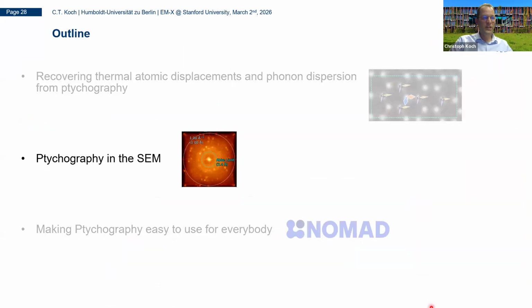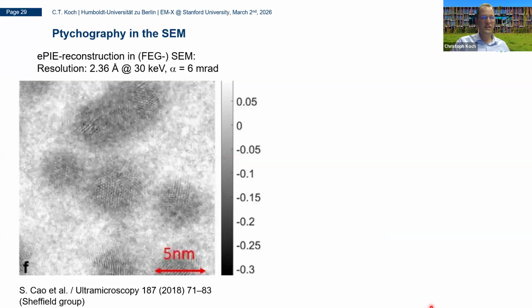Let me just finish with 2 very quick topics. So one of them is this ptychography technique, because it doesn't require necessarily any post-specimen optics, it can of course also be carried out in SEM. So here's some early work by Xiaodong Zou, and she reanalyzed data that was recorded in the Sheffield group, and really was able to produce a 2.3 angstrom resolution reconstruction of these gold nanoparticles on amorphous carbon.